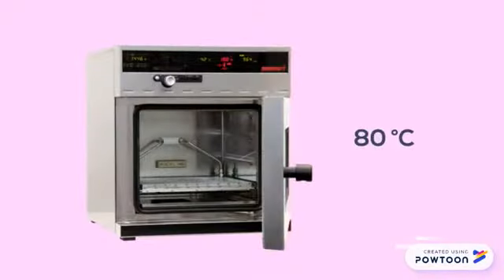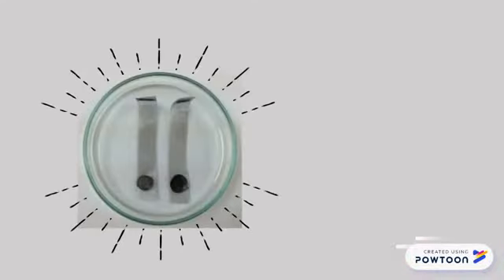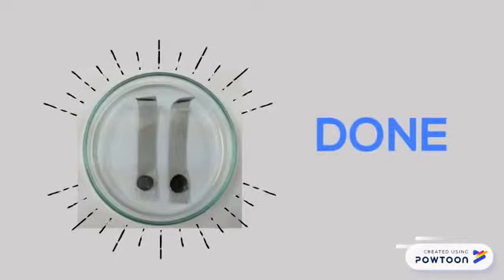Then it will be placed in an oven at 80 degrees Celsius overnight to remove excess binder. The dry slurry will be pressed with a hand pressing machine under 20 tons load pressure for 3 minutes and then dried again at 80 degrees Celsius for 2 hours to ensure the anode is completely dry. Finally, the LVO anode was done by going through those processes.